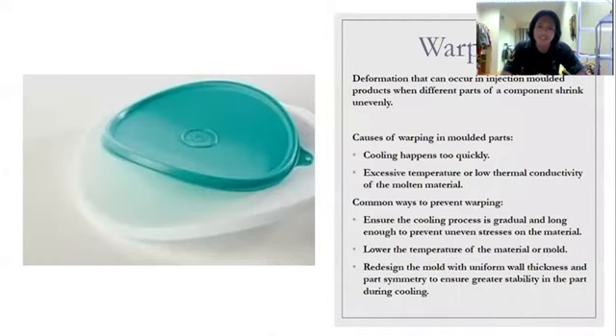So the first defect is warping. Warping is a deformation that can occur in the injection molded product when different parts of the component shrink unevenly. The cause of the warping is the cooling happening too quickly, excessive temperature, or low thermal conductivity of the molten material. The common way to prevent warping is by ensuring the cooling process is gradual and long enough to prevent uneven stress on the material.